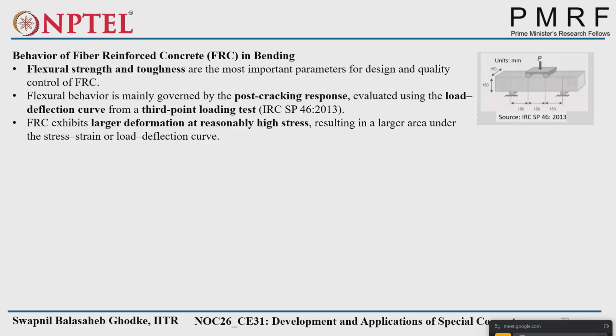Then another aspect of the behavior of fiber reinforced concrete. This is not actually a beam, this is a pavement type of thing, according to IRC SP 46 2013. They want to see the post cracking response. So in pavement design also, nowadays most of them are using fibers along with the main reinforcement. The deflection curve for the 3-point bending test has been given in Indian Roads Congress SP 46 2013. Larger deformation at reasonably high stress results in a larger area under the stress strain or load deflection curve given by the fiber reinforced concrete.